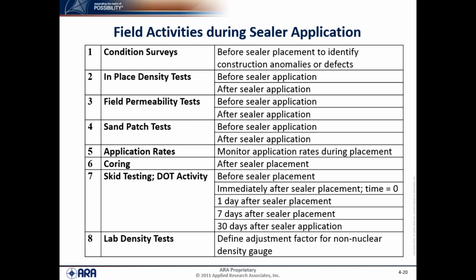Okay, so this just moves now to some of the field activities that were done during the sealer application. I'll go through each one very briefly. We did do condition surveys before the sealer placement, even though the asphalt concrete overlays had just been placed. The reason for doing that is we wanted to identify whether there were any construction defects, like segregation, that we could identify, longitudinal joints, that type of thing. So we did do a condition survey on the controls in each of the test sections prior to sealer application.